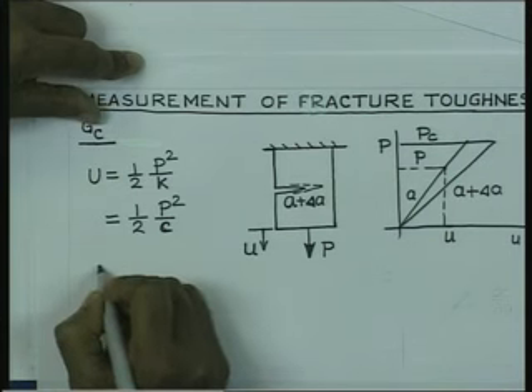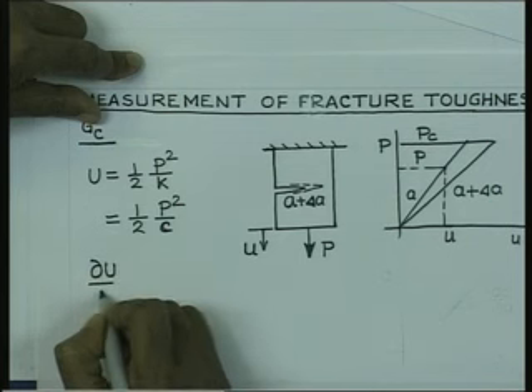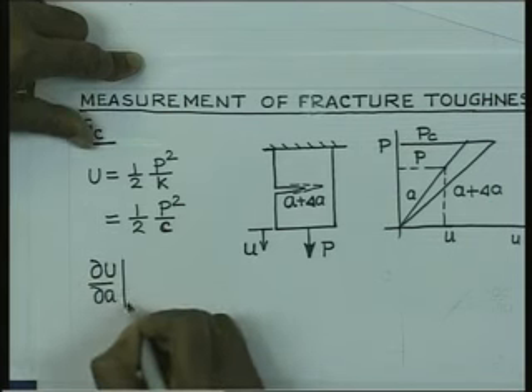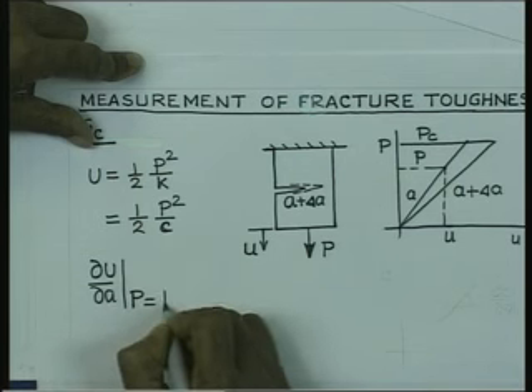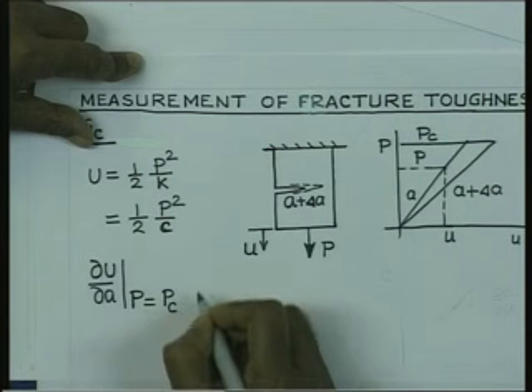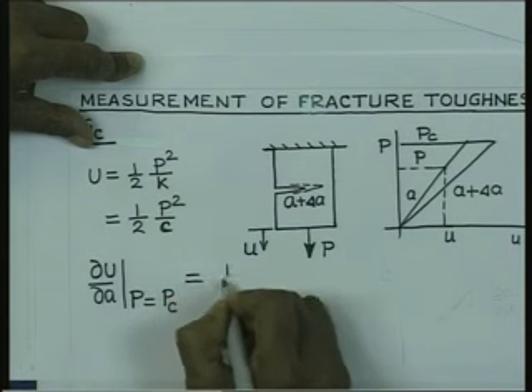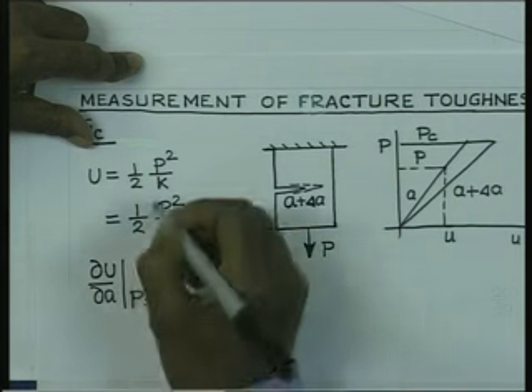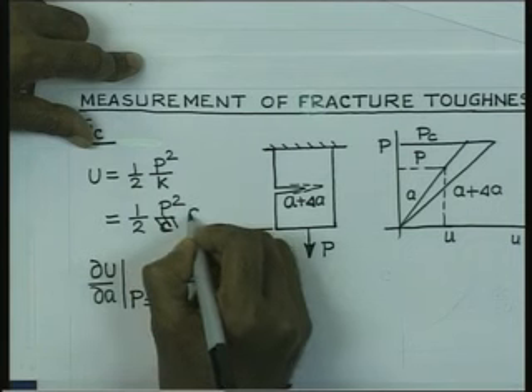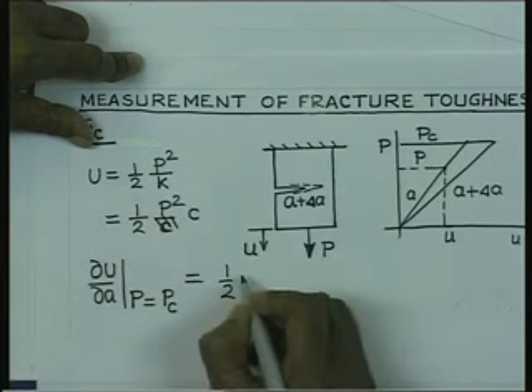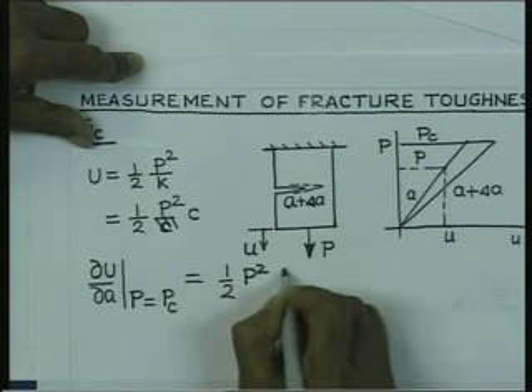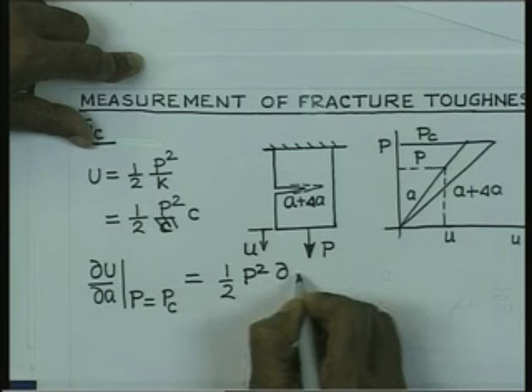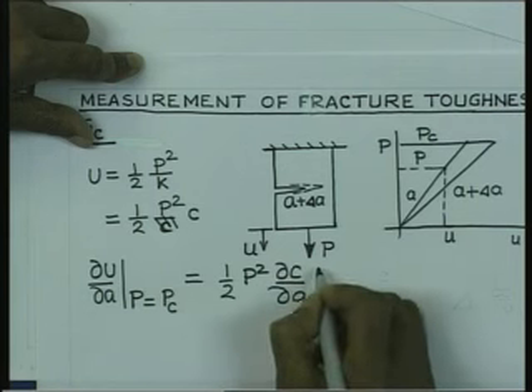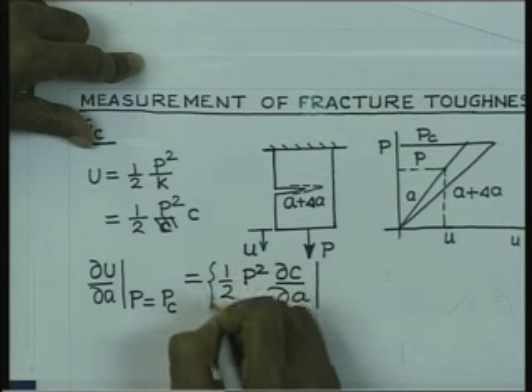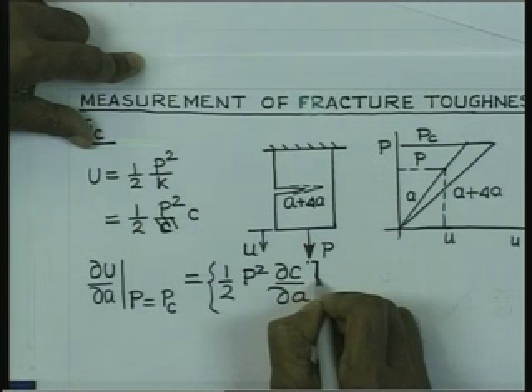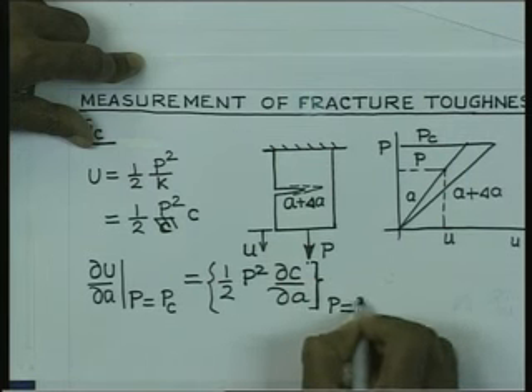If we consider the rate of release of strain energy, delta U by delta A, under a constant load P equal to Pc, then it is going to be given by, I beg your pardon, I made a mistake here, it should be half P square into C, and therefore it is going to be half P square delta C by delta A, and we have to calculate the value for P equal to Pc.